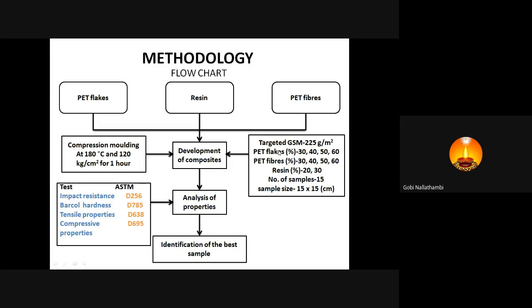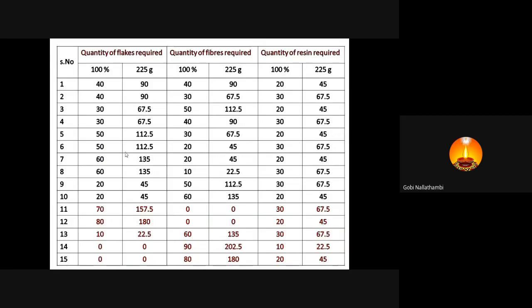So the calculated quantities of flakes, fibers and resin are taken. Then these 3 are mixed by hand mixing. Then it is placed in a die. Then the die is placed in a compression molding machine. We maintained 180 degrees Celsius temperature because the curing temperature of the resin is 180, and the applied pressure is 120 kg per square centimeter for 1 hour. Then we get a product. So this is the combination of the various process parameters to produce the sample.